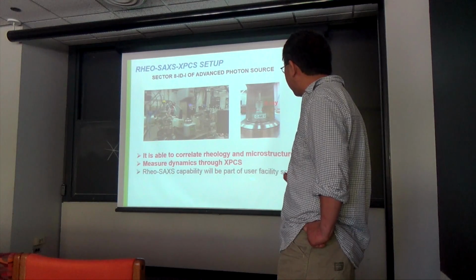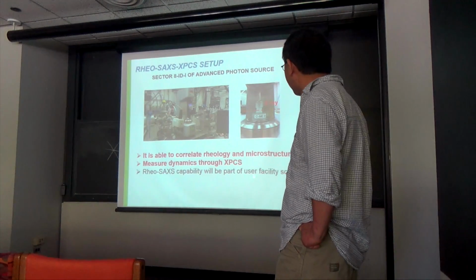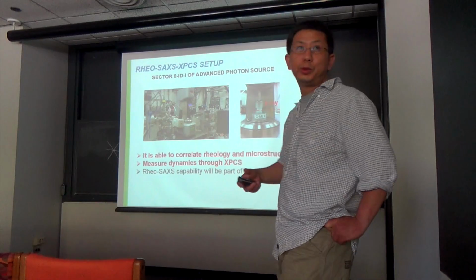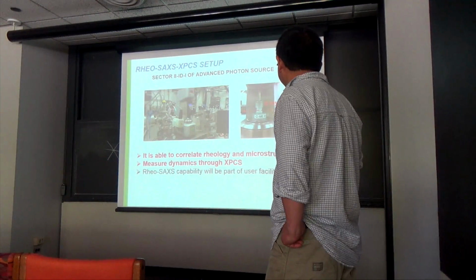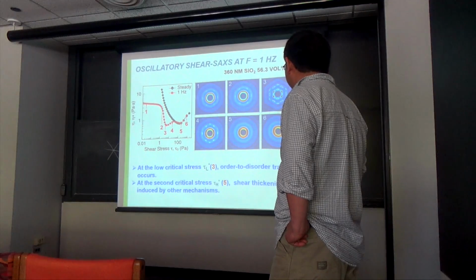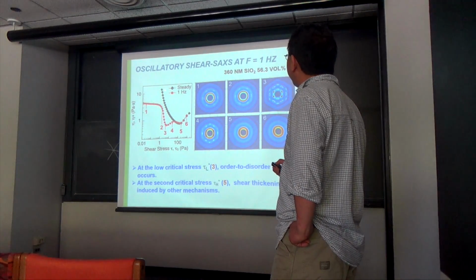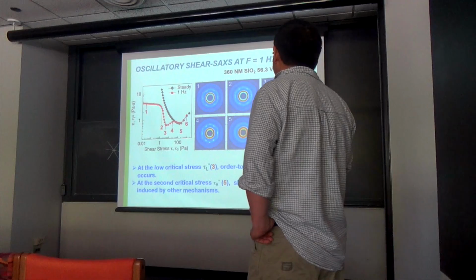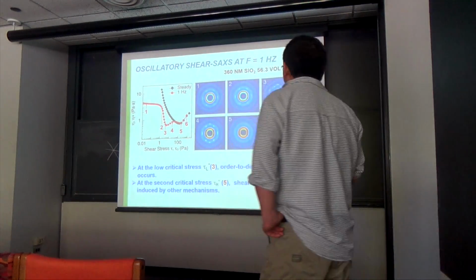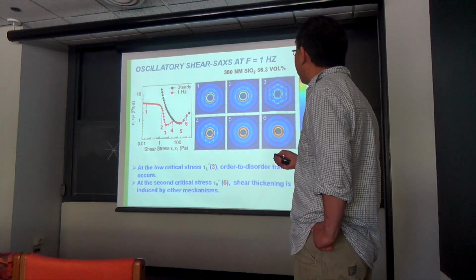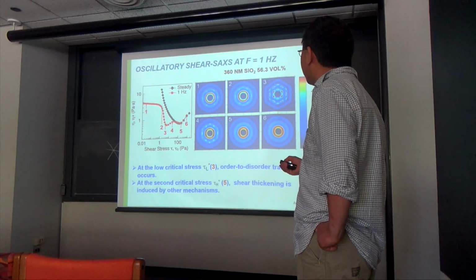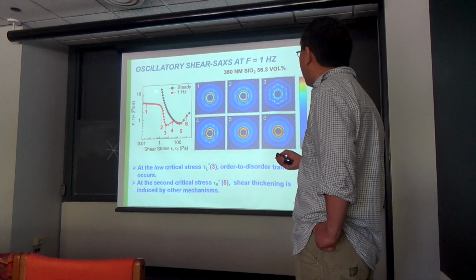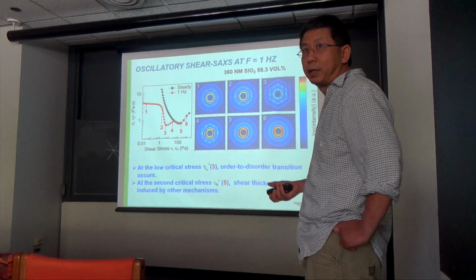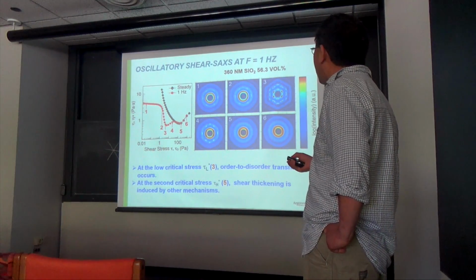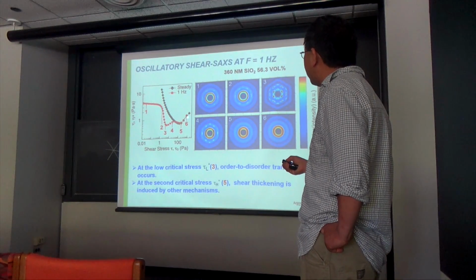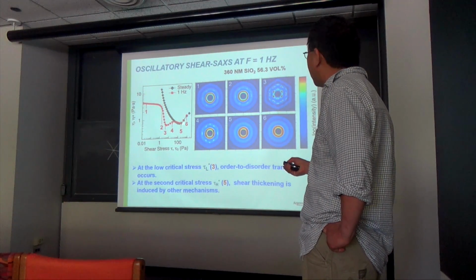And this pretty much is a user facility now. We haven't really advertised it, but we hope to do some experiments ourselves first, especially with our close collaborators. But I'm going to show you one example of what we did. This is 360 nanometer glass spheres. We did oscillatory shear as well as steady shear at a large packing fraction. I believe this one is around 56 percent volume fraction. So you see the shear thinning behavior as well as shear thickening behavior in these colloids.